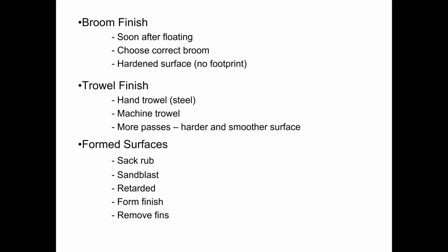One thing not to do with a trowel is to use a trowel in place of a float. Floats have rounded edges. That's on purpose so that they don't seal up the surface of the concrete. A trowel does have sharp edges, and those sharp edges are intended to seal up pores and small openings in the concrete. So if you use a trowel when a float should be used, that means there's still a decent amount of moisture within the concrete that may be making its way to the surface.